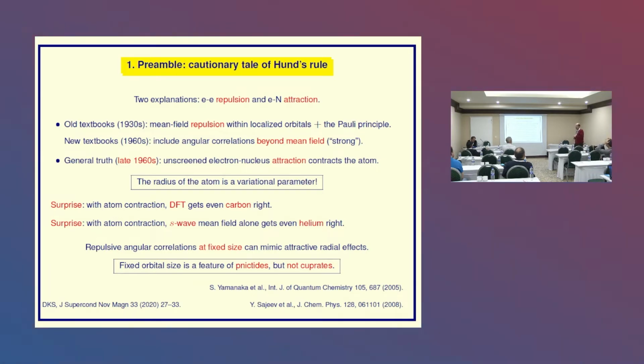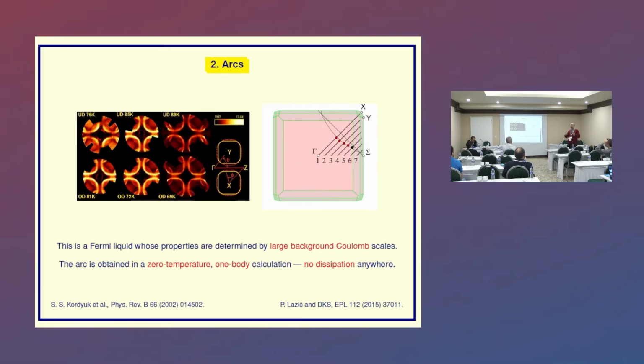While in the cuprates, you have the bridging oxygen. The bridging oxygen allows charge transfer from a correlated atom to an uncorrelated atom, which fixes the size of the lattice, and this is effectively the size of the atom in the lattice, okay? So you have essentially the modern explanation of Hund's rule is active there.